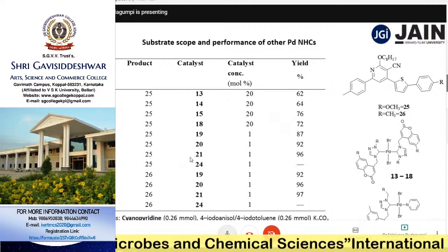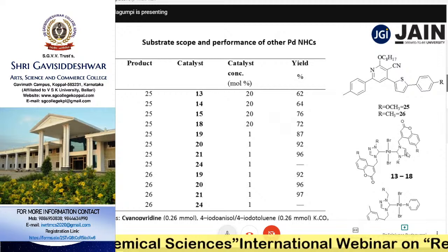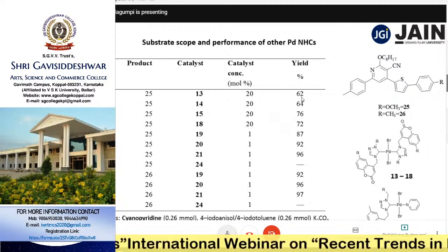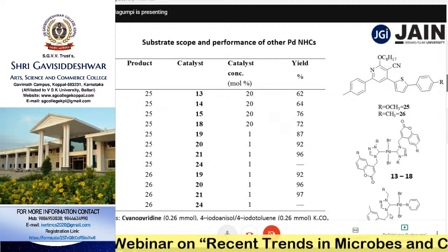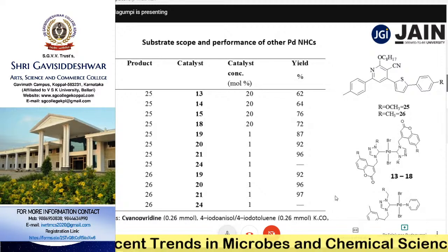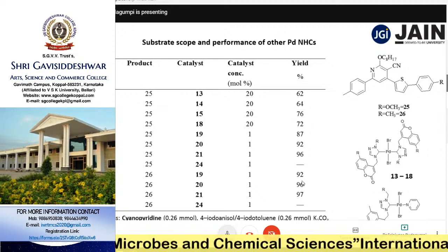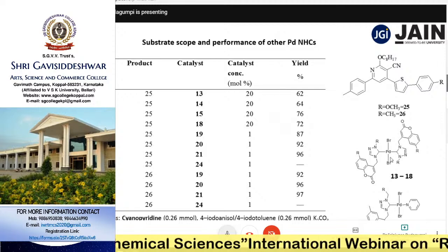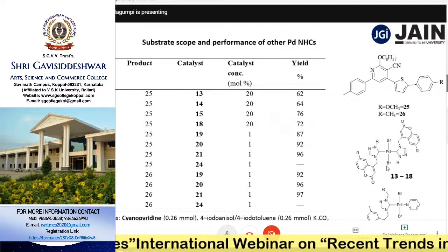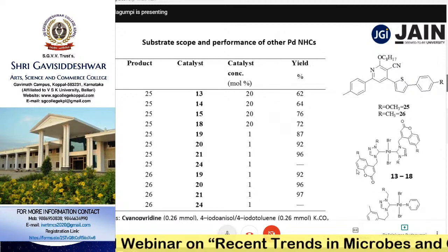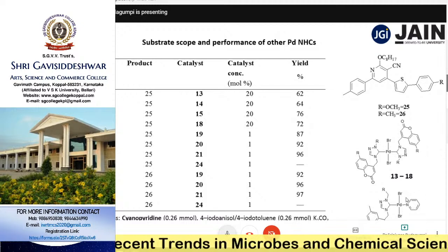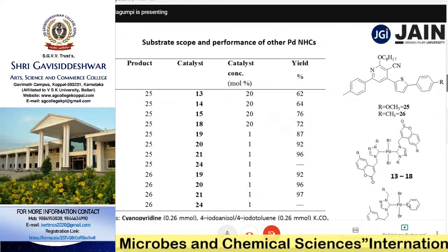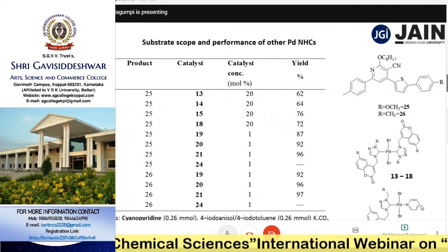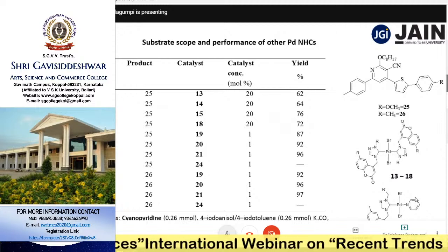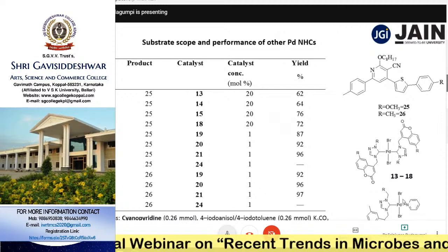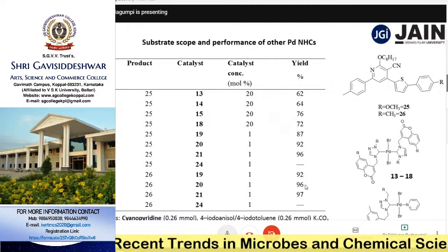Of course, if you look into the structure activity relationship, these complexes have given lesser yields, say 62 to 72%, while the pyridine ones have given yields of 92 to 97%. This is because of the structural differences in these two compounds. Here we have a pyridine ligand, which is easily decoordinated. We call this a throw-away ligand. Because of the presence of the throw-away pyridine ligand, the yield is increased here.